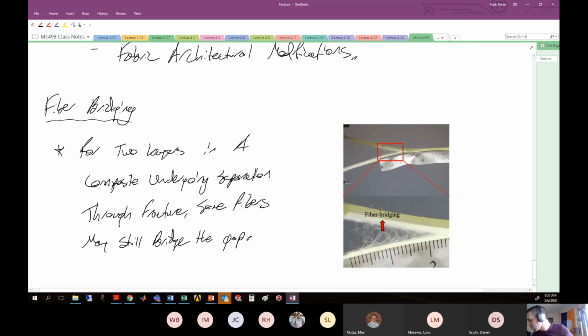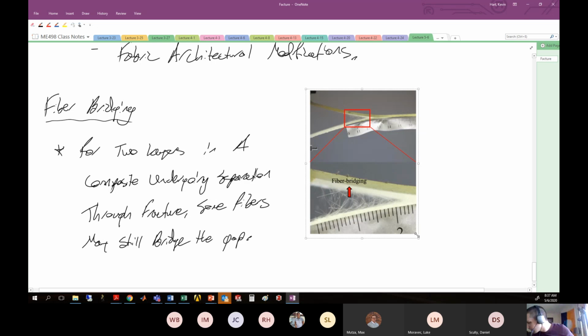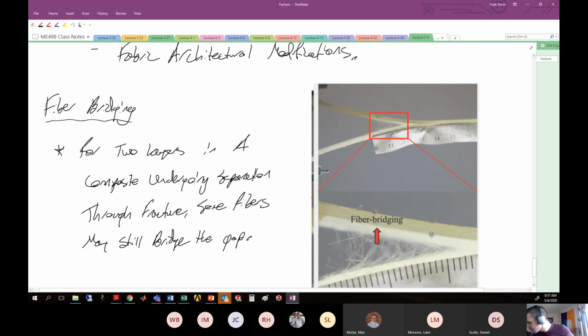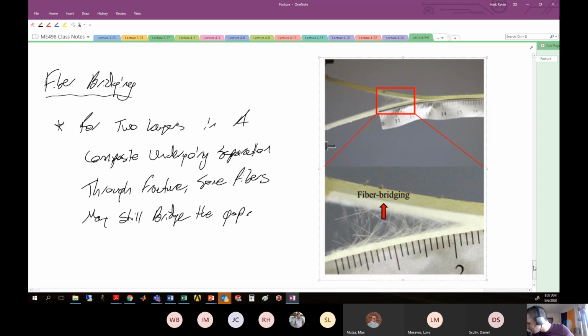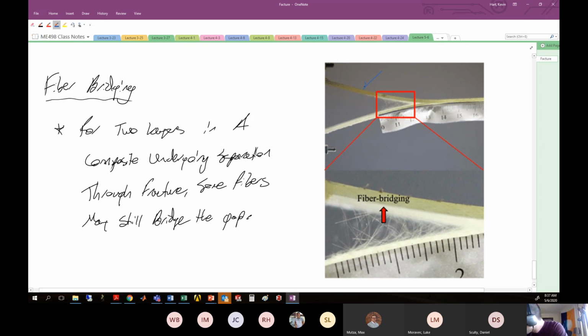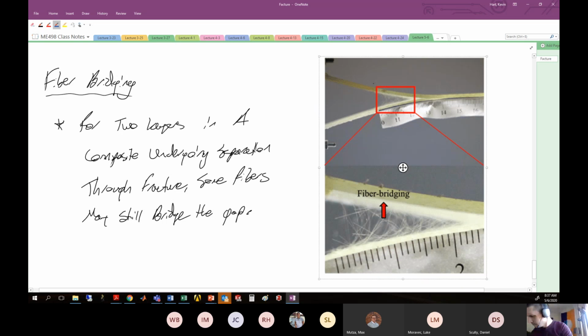And let's take a look at what this actually looks like in reality. So here's an example. This is a double cantilever beam specimen that's being pulled apart. This is a DCB specimen, and it's being pulled apart here and here, so it's being loaded in this general direction. What you see here in the center is all of these fibers from the bottom layer and the top layer, respectively, that don't want to let go of each other. All these fibers are commingled in that crack plane as you pull this open.